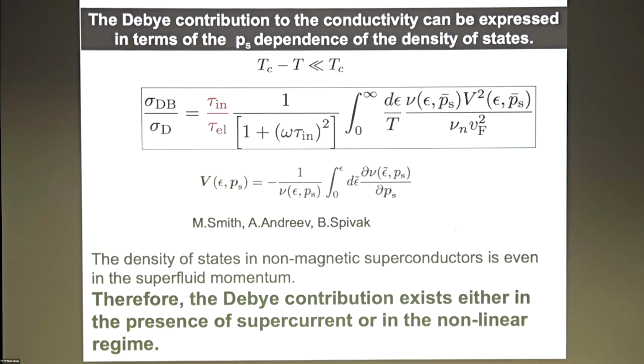Now, if it is, for example, a p plus ip superconductor, then this is not zero even in the absence of external superfluid momentum. And the message here is the following: if you have a superconductor, you measure microwave absorption, and you see the value of sigma significantly larger than its value in normal metal, it's not a conventional superconductor. So it's almost a smoking gun for a new kind of superconductivity.